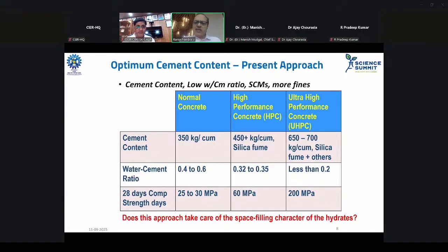In concrete technology, we are all taught in our colleges that if we have to increase the strength, there are two parameters. One is the cement content, another is the water cement ratio. Therefore, if we have to get about 25 to 30 MPa of concrete, maybe the first column, you would see that the cement content is roughly in the range of 350 kg per meter cube, and the water cement ratio is in the range of 0.4 to 0.6.